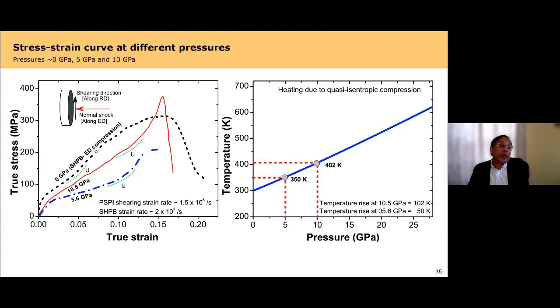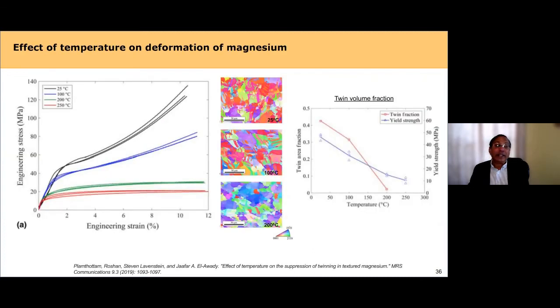That creates complications in the anisotropy of the material. One of the surprises we had was that when we did split Hopkinson pressure bar experiments, it showed higher strength than the plate impact experiments. We have explained this using the operative mechanisms. When you have higher temperatures, it favors slip rather than twinning. When you compress it along the axis, there should be extensive twinning, and the increase in temperature suppresses twinning, and this is shown in the literature.